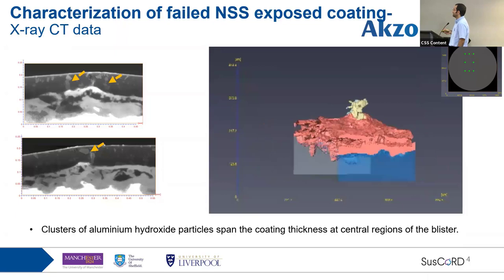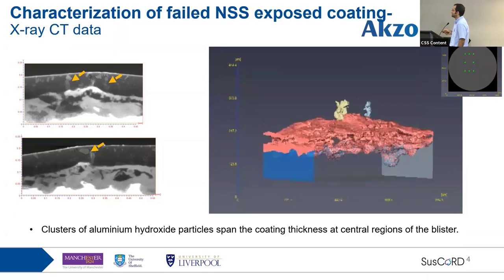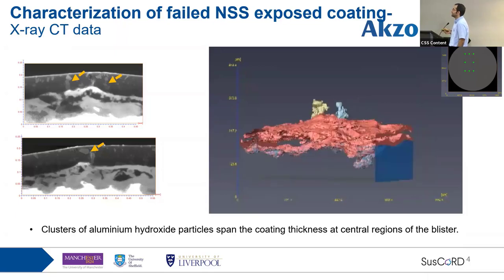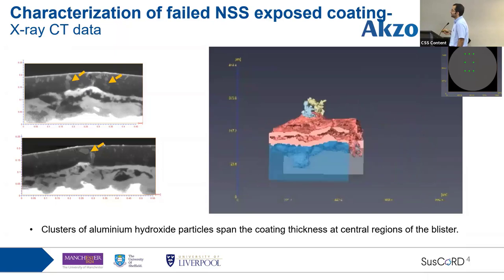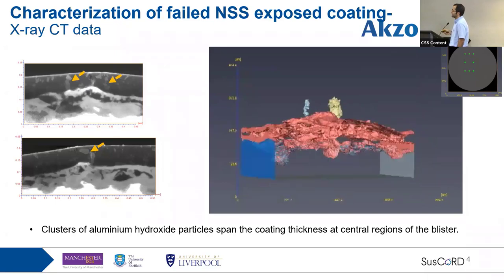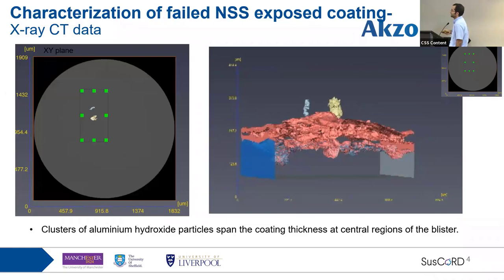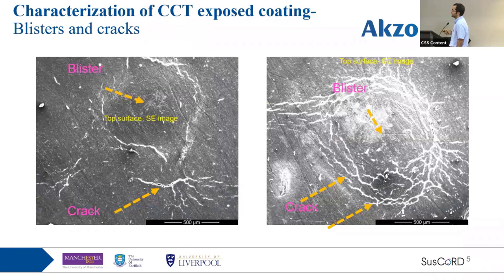And then if we segment it and show it, we can see that there are actually not only two pigments there, but a cluster of pigments that elongates through the thickness of the coating. And these are the positions of the pigments within the blister, so almost in the central region. And I think this can be the reason for the failure.